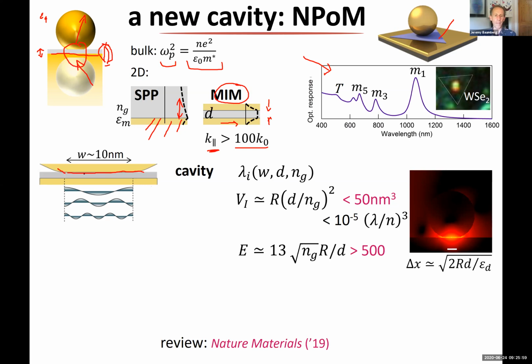So what happens is you have a discontinuity at the edge of the facet. So this is the insulator metal waveguide, but now those plasmons bounce against the two walls here. So they bounce backwards and forwards, and they form a sort of little cavity. It's a strange cavity because the walls are actually here and here, if you like. There's the sort of discontinuities which act as the mirror, and it's only a few, 10 nanometers or so long. But because the mode is traveling so slowly, that's actually fine.